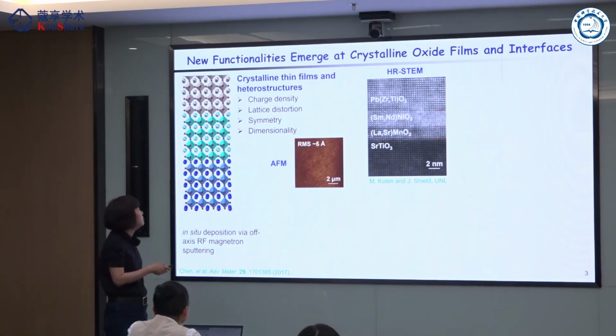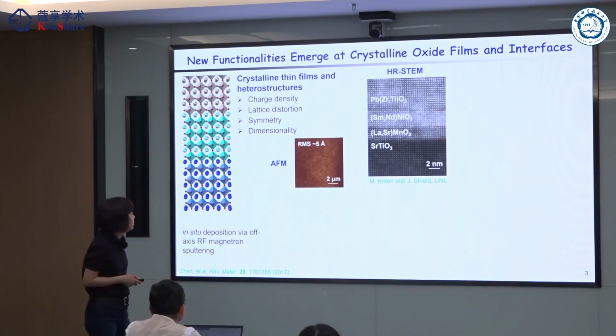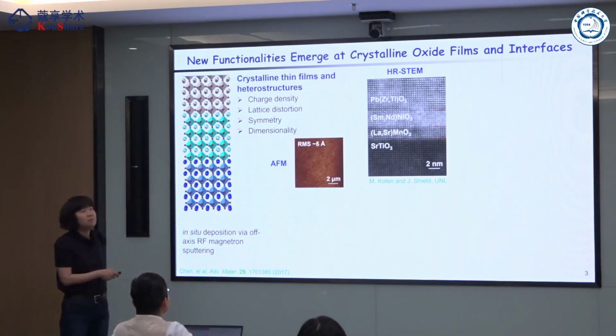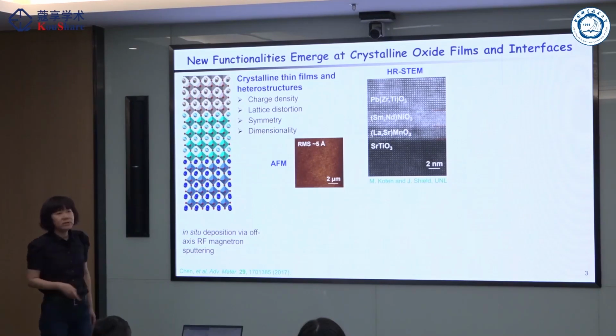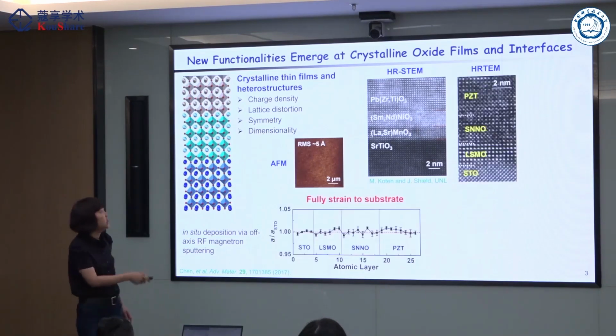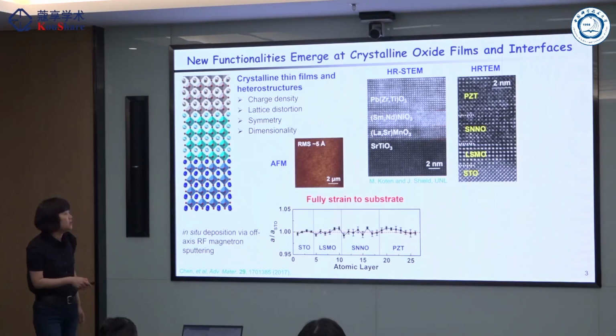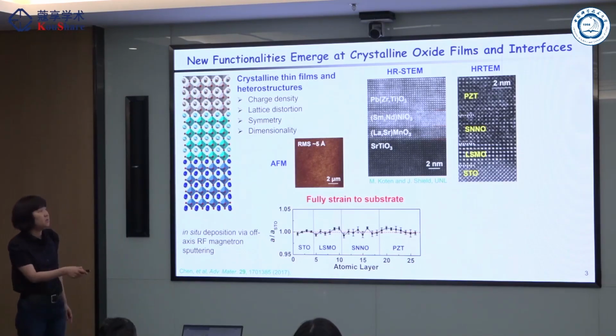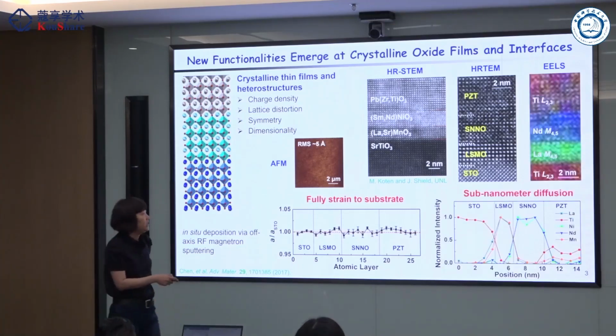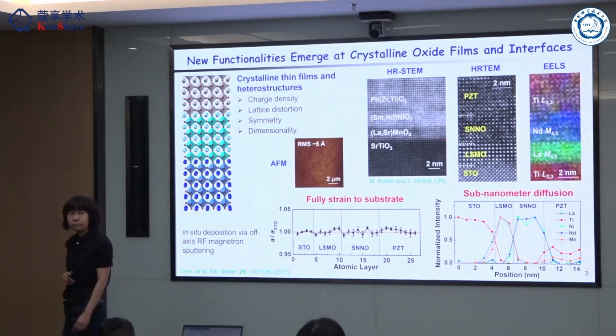And you can see that we can produce very high quality thin films with a smooth surface morphology and high crystallinity. If you look at the TEM studies, basically those have a very sharp structural interface. The lattice is well strained, and it is also chemically sharp.